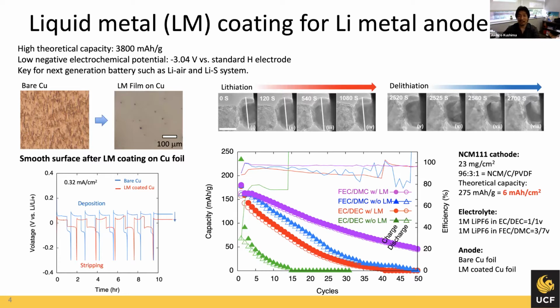But the key is that lithium causes lots of issues. For example, it can form dendrites, very sharp lithium pillars that can extend to the other side into the cathode and cause a short circuit, and that can cause fires. Also there are lots of reactions going on, and you want to prevent all these unwanted reactions with the lithium. So here I've been developing coating technologies on the anode side to prevent this lithium metal dendrite, so you can extend the cycle lifetime.